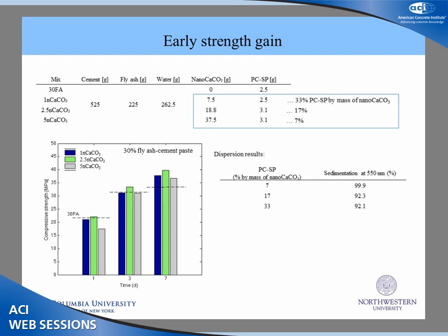So if you look at the mix design of each of the pastes, they all have the same cement, fly ash, and water content, and varying additions of the nanocalcium carbonate, and also varying additions of the PC superplasticizer. Now if we look at the mix with 5% calcium carbonate, if we express the PC superplasticizer by percent by mass of nanocalcium carbonate, it's 7%. And the reason we have to limit the PC superplasticizer is, remember, its purpose is to change the rheology of the paste.